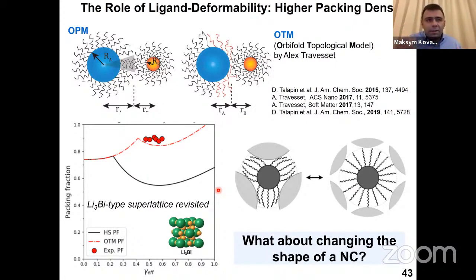So what can happen is that when two spheres approach each other, the ligands on the smaller one can bend away, can create these vertices, and therefore they can allow a more compact lattice, so that these two spheres can approach each other closer when one of the spheres can bend away their ligands. And so this is stabilizing the higher packing density. So if that happens, you can expect that your overall stability of the lattice will be higher because you can stuff much more material per unit volume. And for spheres, this has a noticeable effect only in those structures where you have small coordination numbers. If the coordination number is high, there is simply no space to bend away these ligands.